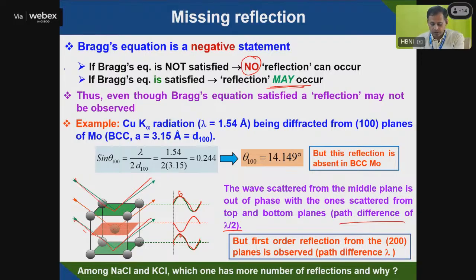Since it doesn't satisfy that phase relation, this peak, from the center plane, you will not be able to see that particular reflection. That means the 100 plane reflection of the BCC molybdenum structure. This is a BCC crystal, with an atom at the center and atoms at all the corners. So 100 is missing.